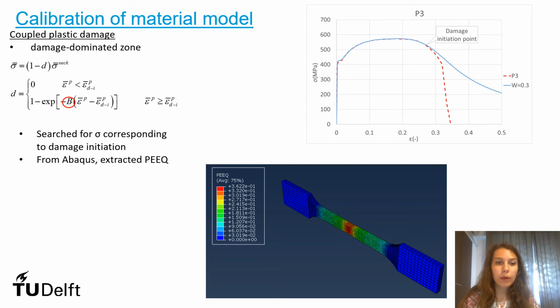Therefore, parameter B has to be calibrated again using the finite element method analysis. We can see that the stress strain curve from the test and also from the simulation agree very well up until the damage initiation point. Therefore, to calibrate parameter B, I searched for the sigma that was corresponding to damage initiation, and in Abaqus I extracted the plastic equivalent strain.